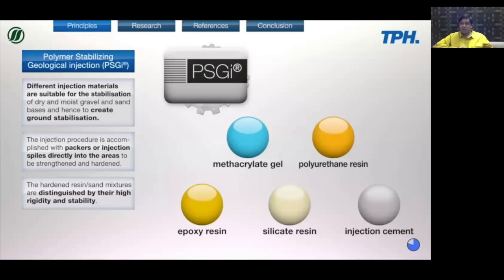It is based on the basic silica backbone, that is silicon dioxide backbone. So it reacts, and we can make different things out of it. It can be a highly foaming kind of material, maybe a tough consolidating kind of material, or something slightly flexible that you can use to bond ballast or things like that. So a lot of applications come up using silicate resins, and they are especially good to put into areas where the foams can foam up to 70 to 80 times their initial volume.